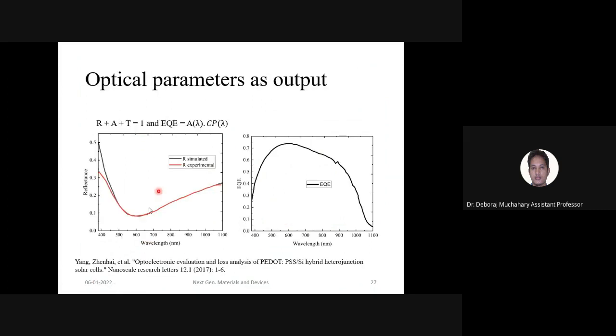Now here I have some data of reflectance collected from this paper. The red one is the experimental, and this is the simulated. What they have done is they used FDTD methods and found the reflectance from that device. If you get the reflectance, and if the transmission is 0, then you can easily calculate what is the absorbance. And from this absorbance you can calculate the EQE, that is external quantum efficiency. So this type of graph for external quantum efficiency is observed.